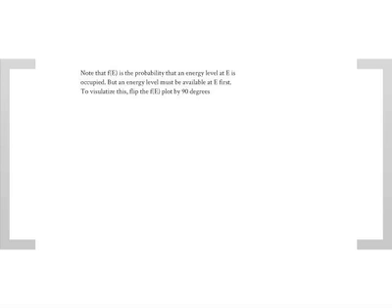Recall that if you have a band gap in a semiconductor, within the band gap there are no energy levels. So even though you might have a finite probability that electrons could exist within the band gap, there are no available energy levels, so they cannot exist. Okay? So F of E is not the full story. You have to understand how many energy levels are available as well.